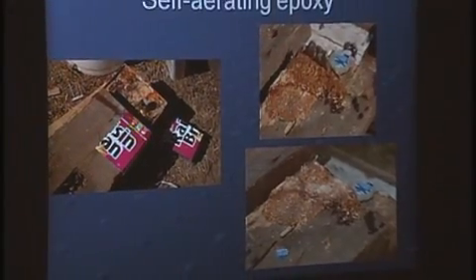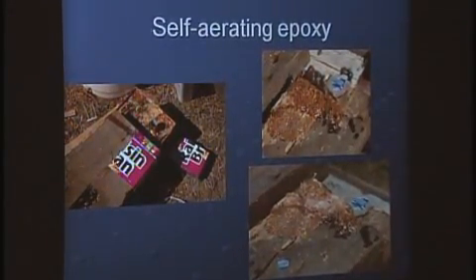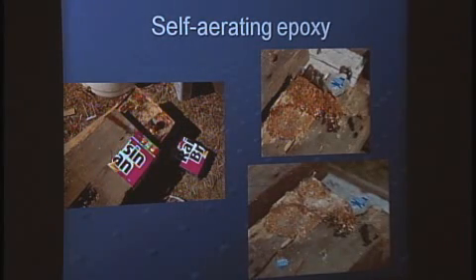And epoxy of that mass gets so hot that it actually boils. It's very hard to get a picture of boiling epoxy, I'll tell you, but I was actually able to get it to boil in place after filling it here. And I should back up and say I first sized all the surfaces with the epoxy just by itself. And since it was a fairly thin coat of epoxy wicking into the end, it actually penetrated very far into the wood. This is a case where I did want very, very deep penetration into the wood.